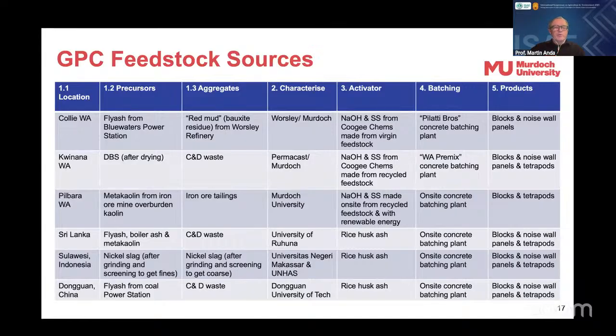If we go to somewhere like Kwinana, which is a large industrial area in Western Australia, that has a large lithium industry there. So the DBS is delithiated beta spodumene. That's an industrial byproduct of refining the lithium. And you could in fact mix that with construction demolition waste, and then add the activated chemicals and use local batching to produce a range of products from that. We can go to the far north of Western Australia, and we can use the iron ore tailings from the iron ore industry there, and we can use metakaolin derived from kaolin clay in the overburden.